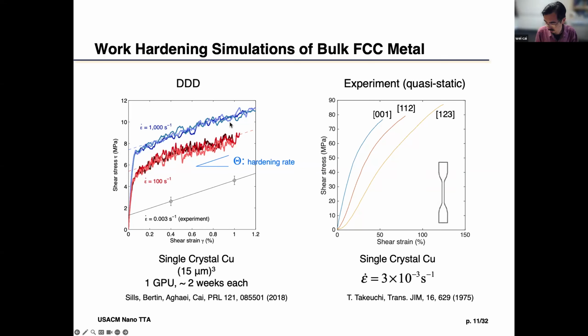So we can say, okay, can we then compare with experiments, and on the other hand, can we also try to explain quantitatively what's the origin of the strain hardening behavior. On the right are shown those experiments done in the 70s, stress-strain curves. So we're loading the sample. Actually, this is along the 001 orientation, so we should compare with this curve, the blue curve.